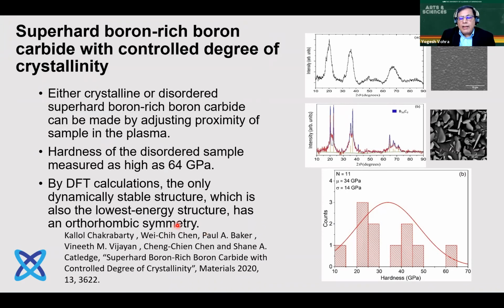Another work actually done by Dr. Catledge's group at UAB, just like we showed for the nanocrystalline diamond structures, you can also grow a nanocrystalline B50C2 type of material. So this may have parallel applications like we talked about, having an additional attractive feature of low friction and low wear and a very high wear resistance, and at the same time be a high temperature coating in applications.